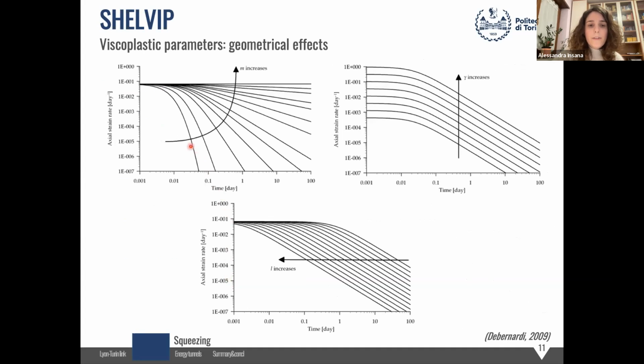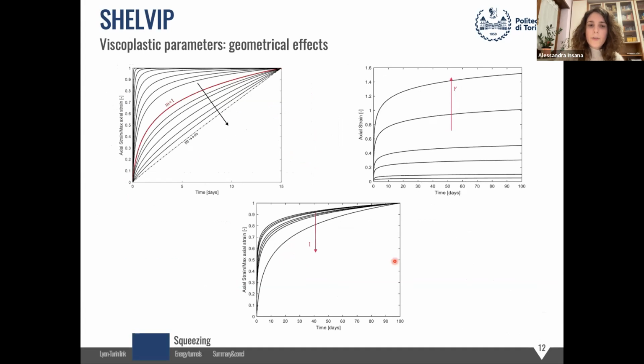So in terms of geometrical effects of these parameters, if we increase m, the slope of the curves of the axial strain rate against time decreases. If we increase gamma, the curves move upwards, while if we increase L, then the curves will stretch towards the left. So if we look not anymore at the plane of the axial strain rate, but of axial strain, then the role of m is to change the shape of this curve. We've said it's called shape factor. Gamma changes the amplitude of the strains, and L changes the time scale.